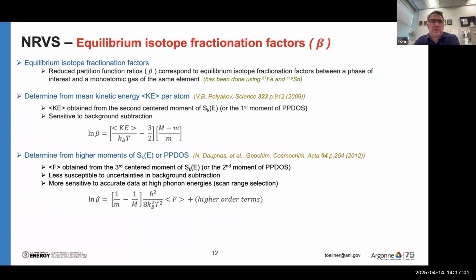Another quantity of interest is equilibrium isotope fractionation factors. It's popular amongst geochemists. One approach is to determine it from the kinetic energy. One can get the kinetic energy per atom from the second moment of the phonon excitation probability density. Unfortunately, it's a little bit sensitive to the background, because the background is also an even moment, so it has a non-negative second moment. And so this background subtraction becomes an issue.